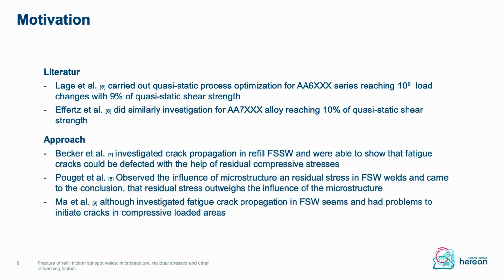So I tried to go for a different approach, as I've shown myself, that it was able to deflect fatigue cracks with the help of residual stresses. And there's also different literature about that. For example, Pouget observed the influence of microstructure and residual stresses in friction stir welds and came to the conclusion that the residual stresses outweigh the influence of the microstructure.